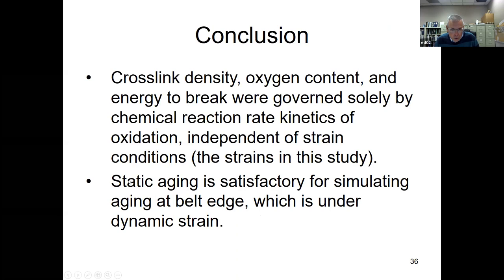Based on this study, no-strain aging is satisfactory for simulating aging in a belt edge, even though in service the part is under dynamic strain for part of its life cycle.